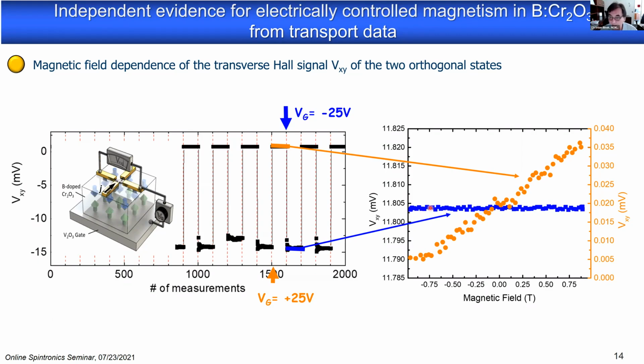So our interpretation is here we have the system in a state where the antiferromagnetic order parameter and the boundary magnetization is primarily normal to the plane. Here, the antiferromagnetic order parameter is in the plane, and therefore the torque on the magnetization is at maximum, and therefore we see, if you apply a magnetic field, a field dependence of that signal.